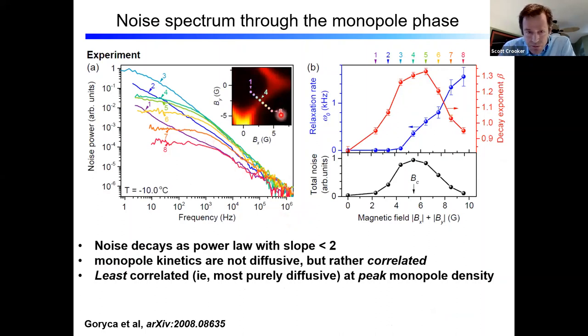So here we take noise spectra as we walk through this monopole phase. And you can see that not only does the characteristic time scale of these fluctuations diverge near this monopole phase, but also the slope with which this noise decays. It decays as a power law, on a log-log scale, and that slope is less than 2, okay? So noise decaying with a power of 2 is what you expect for free diffusion, just a random walk. A slope of less than 2 indicates that the kinetics are not diffusive, but are rather correlated.